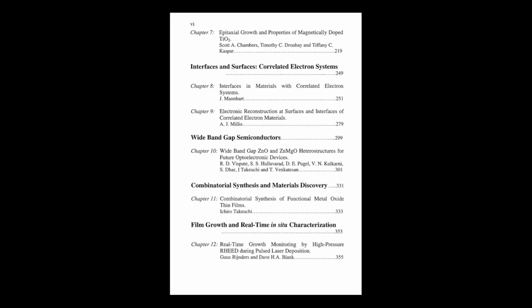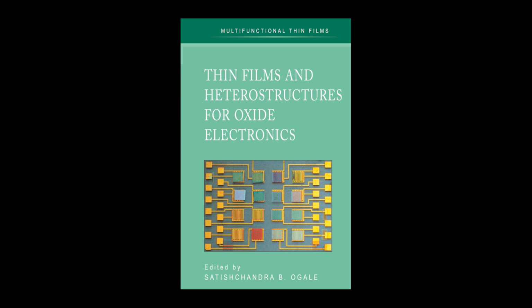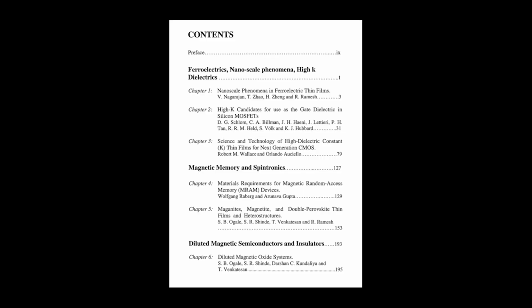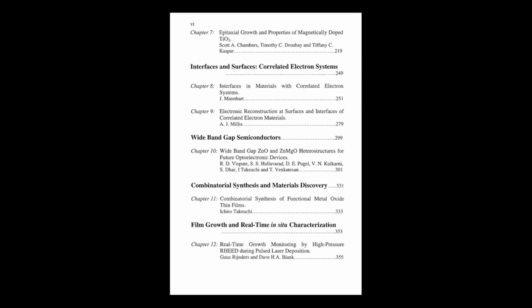Remember, SiO2 is 3.9. Huge improvement. And it ticked all the other boxes too. Stable with silicon. Check. High band gap. Yep, 5.6 eV. Very good. Low defects. Seemed promising. It even had a decent lattice match to standard silicon, only about a 1.3% mismatch.